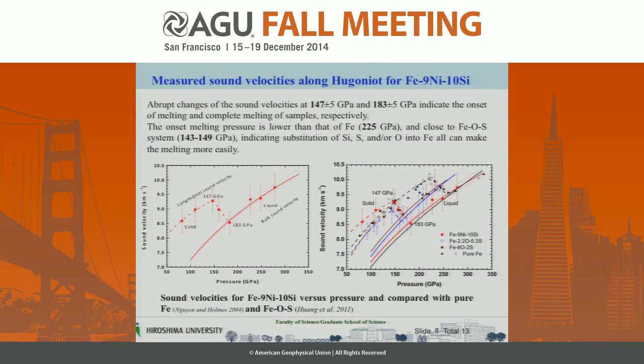This next figure shows our measured sound velocity along this Hugoniot by the optical analyzer method, and the next figure shows the results. We can see there are abrupt changes along the Hugoniot, indicated at 147 GPa and at 183 GPa. They are the onset of melting and the complete melting of our sample, respectively. These 3 points indicate the solid longitudinal sound velocity, and these 4 points indicate the liquid bulk sound velocity. This point is located in the partially molten region.